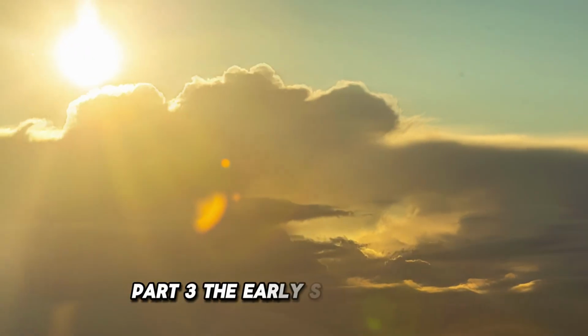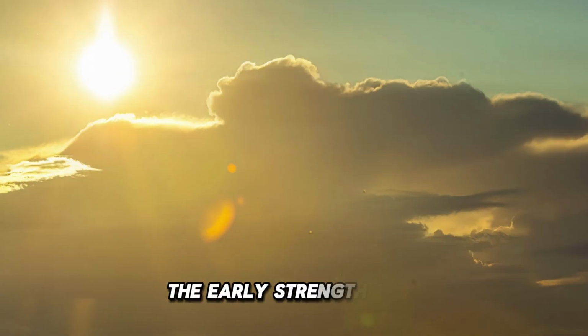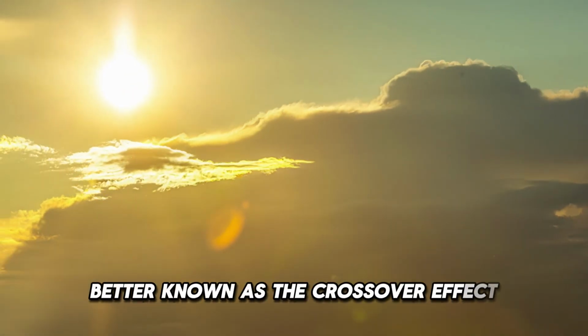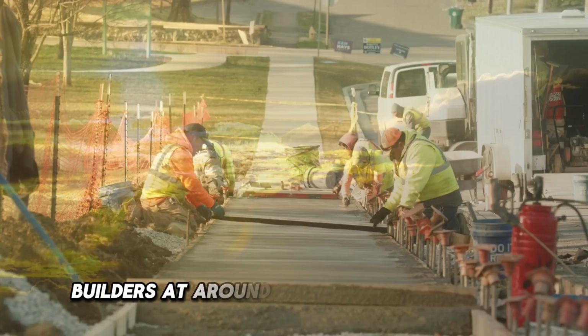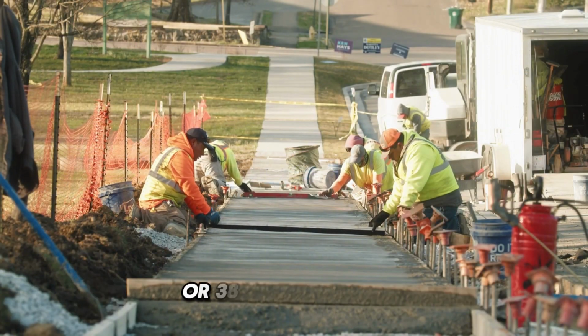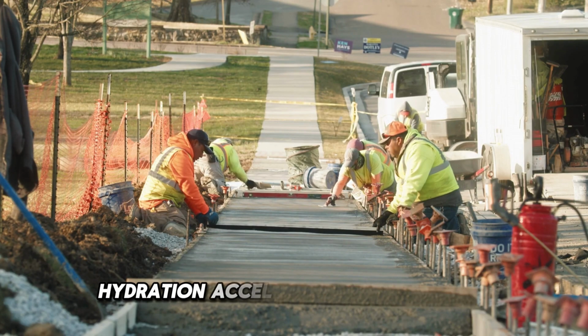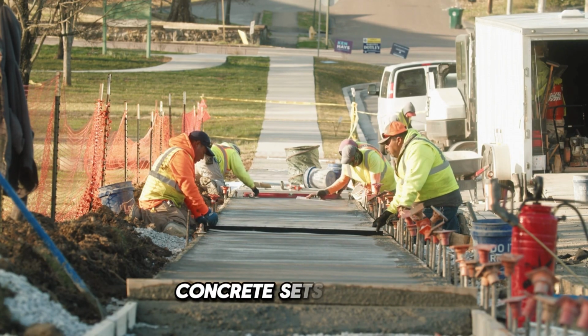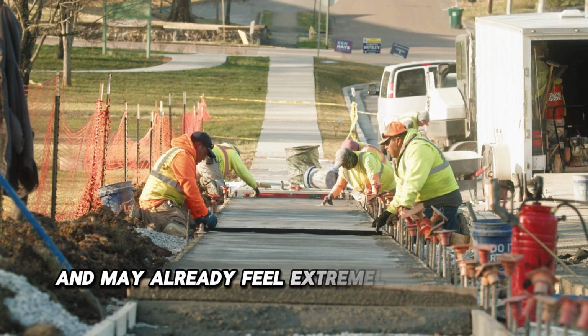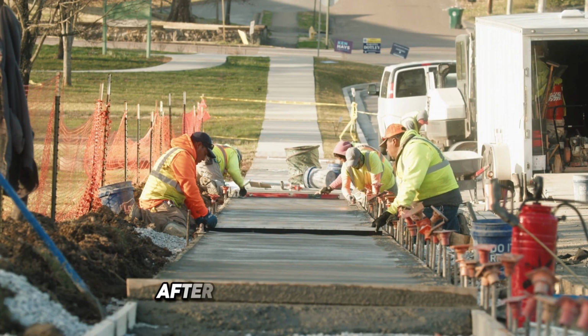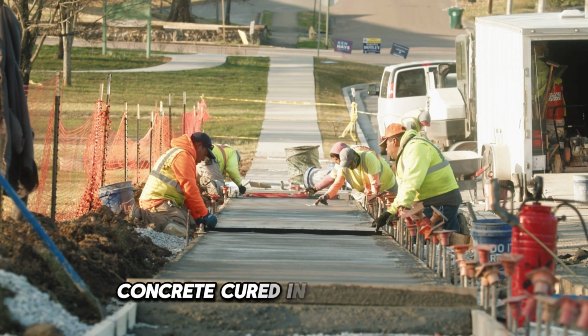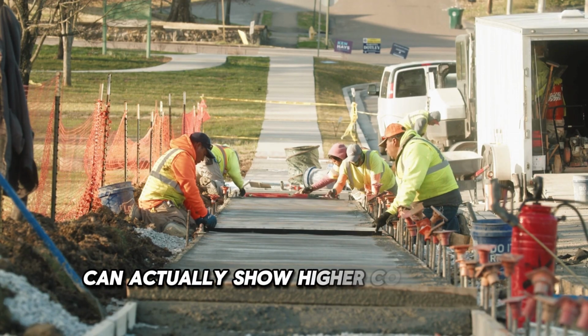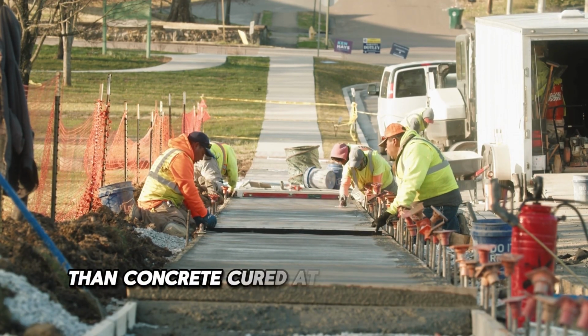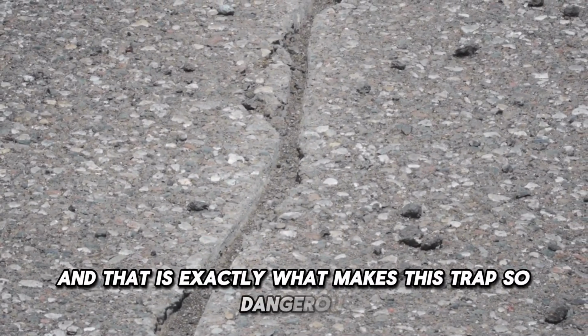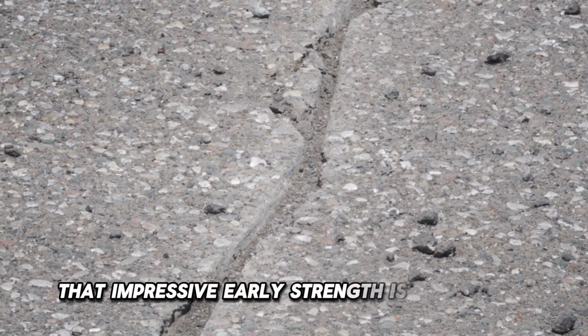Part 3. The early strength trap. The early strength trap, better known as the crossover effect, has fooled countless builders. At around 100 degrees Fahrenheit, or 38 degrees Celsius, hydration accelerates dramatically. Concrete sets quickly, and may already feel extremely solid within 24 hours. After 3 or 7 days, concrete cured in hot conditions can actually show higher compressive strength than concrete cured at around 73 degrees Fahrenheit. And that is exactly what makes this trap so dangerous. That impressive early strength is an illusion.